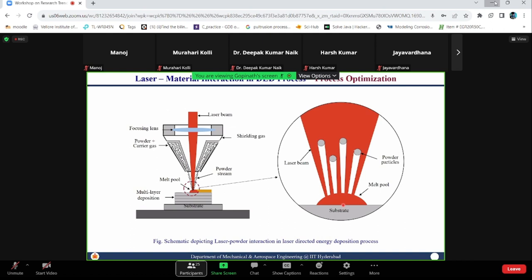So in reality, this is how it looks. Okay. This is the nozzle. The powder is coming through it and the laser is also coming. And at 20 mm SOD, we are keeping this gas jet and trying to blow away the powder, so that whatever remaining energy is available comes and falls onto my power meter, telling me exactly what is happening. Okay.